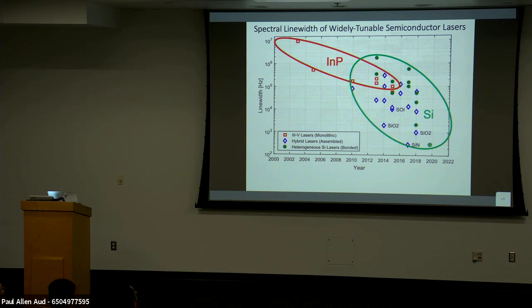So if you look at all the indium phosphide tunable lasers, there's a lot out there. It's been done for 20 years now or 30 years now. But they're really limited in bandwidth to about 100 kilohertz sorts of numbers. But all the silicon groups, and there's probably 5 or 6 groups around the world making tunable lasers, are getting much lower line widths. This is 1 kilohertz. So this is down just a few hundred hertz line widths. And I'm fully confident that we'll get below 100 hertz this year.